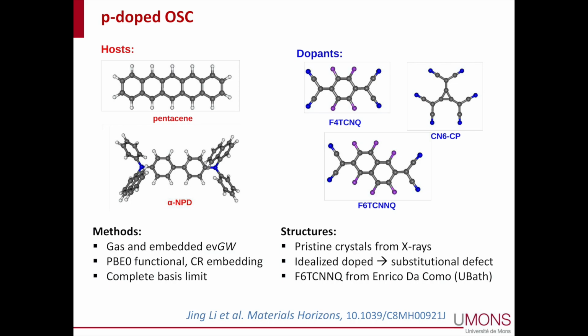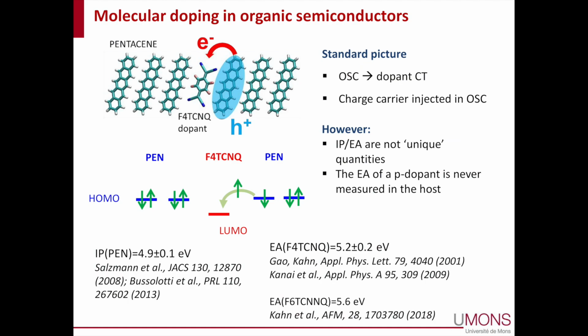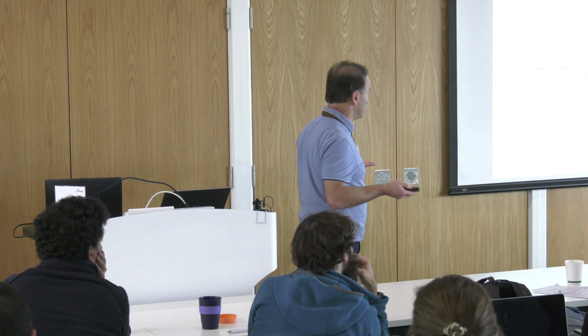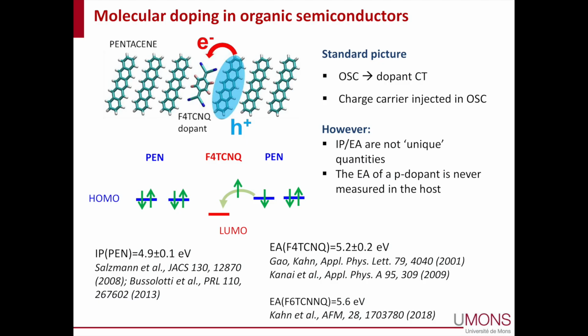It has implications also for doping. For instance, we looked at p-doped material. Host molecules like pentacene and alpha-NPD can be doped with a strong electron-withdrawing molecule like F4TCNQ or F6TCNNQ, shown here. And the picture is very simple in principle. You would expect that if the LUMO energy level of F4TCNQ, the dopant, is below the HOMO energy of the host, then you can have a full charge transfer in the ground state, and that gives rise to an ionized dopant and a hole sitting on the pentacene. The hole, the excess positive charge, can move in the organic semiconductor and could contribute to conductivity.